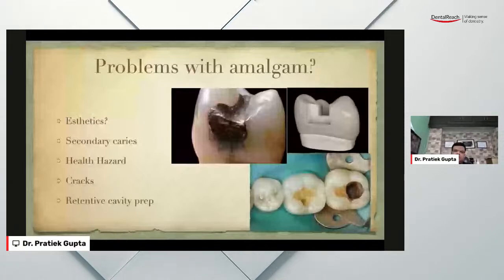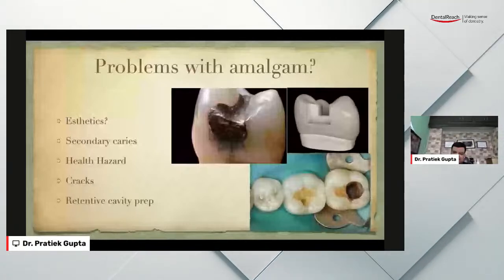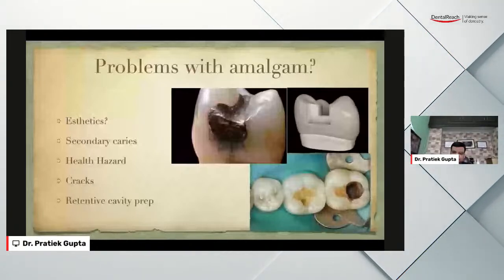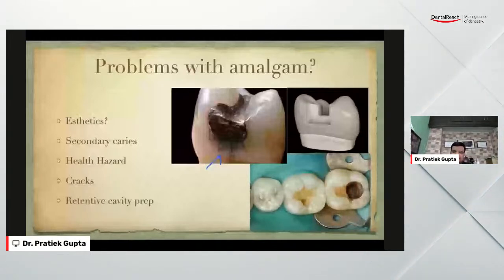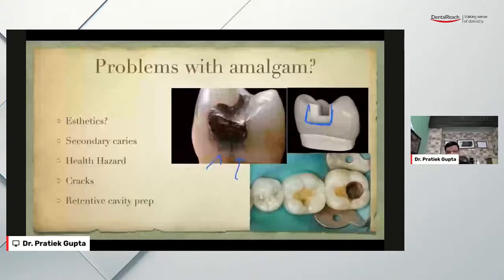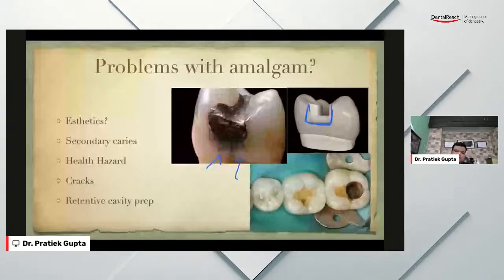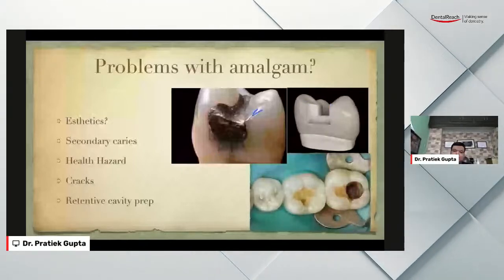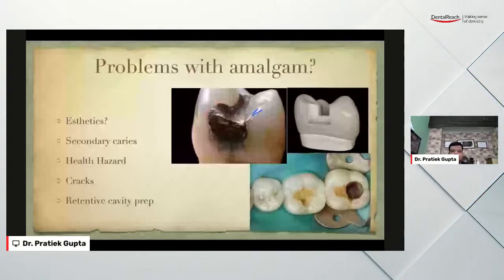One, that it caused cracks onto the teeth, cracks like these. And second, it needed a retentive based cavity preparation. The problem with the retentive based cavity preparation is you need to remove, like Dr. G.V. Black said, a minimum of 1/3 the intercuspal distance to have enough strength with the amalgam. You cannot have small amalgam restorations and expect them to last. So they would be retentive, and that my friends was the biggest flaw with amalgams, the cavity design.